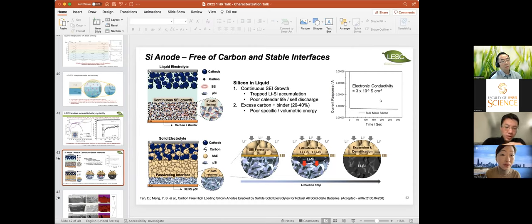Right, and you also mentioned that after you strip it away, maybe 20% of lithium actually stays in the anode. Does that mean the first cycle strip, or at the end of a few hundred cycles? First cycle. Yeah, we were very badly criticized by LG, right? Because nobody likes the first cycle having 20% capacity loss. We can only do that because our cathode was dry processed, so we have very high loading on the cathode.